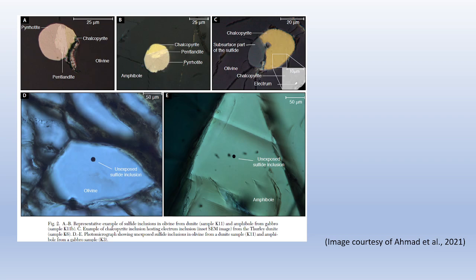What makes this dataset so unusual is not simply that sulfide inclusions exist, you can find them in other deposits and other geologic settings, but the extraordinary fidelity of the preservation, the presence of precious metal alloys like electrum, and the fact that all of this comes from a lower crustal cumulate. It's an environment where sulfide saturation isn't typically expected without crustal contamination. Together, these inclusions provide rare, direct evidence that even small amounts of sulfide in the lower crust can capture copper, gold, and PGEs, stripping them from the magma long before it reaches the upper crust. And that reshapes how we think about the deep controls on metal budgets in arc magmatic systems.